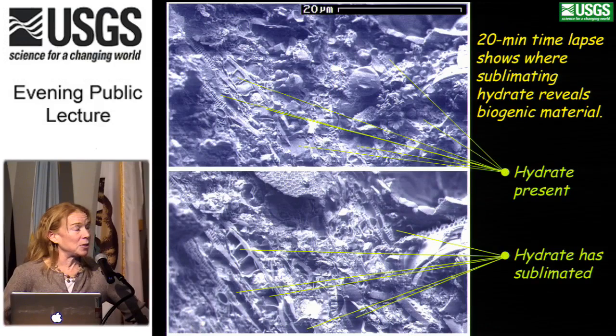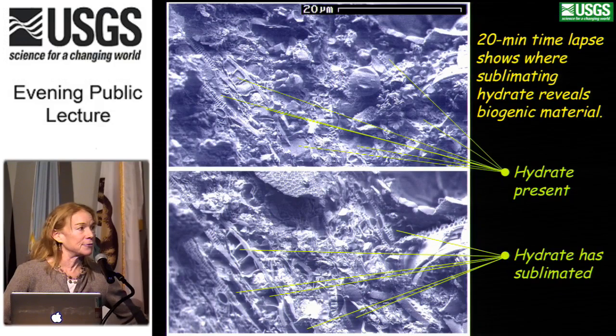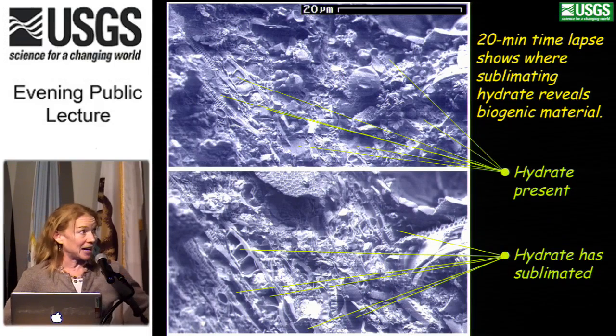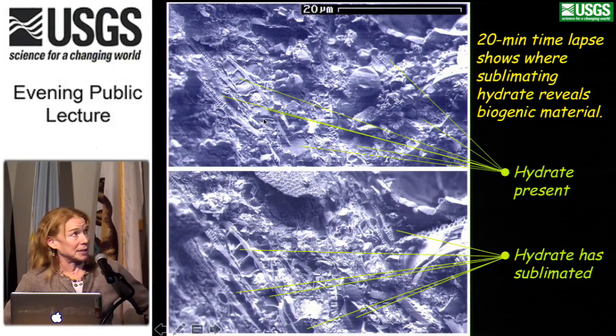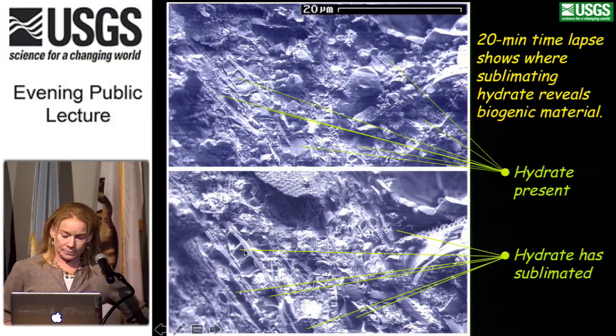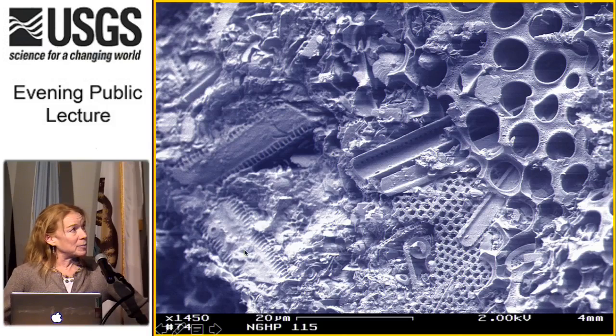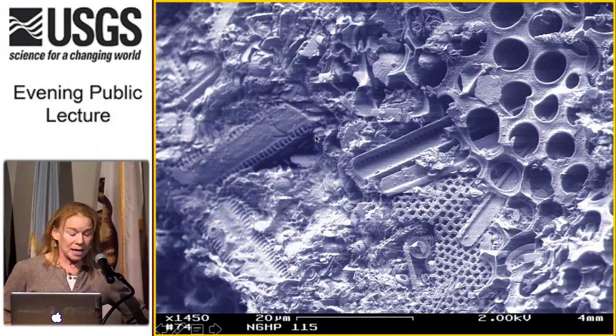This particular sample was greenish macroscopically. It had a lot of biogenic material, little skeleton fragments and nanofossils, as well as volcanic ash and clays and silts. What was interesting about this sample is that the hydrate sublimated very rapidly, in about 20 minutes. And as it sublimated, it revealed the beautiful structure within the marine sediments, and the little nanofossils were all embedded in it. So after the hydrate sublimated, we could see these beautiful diatom fragments and start looking more closely at sediments that form with these hydrates.